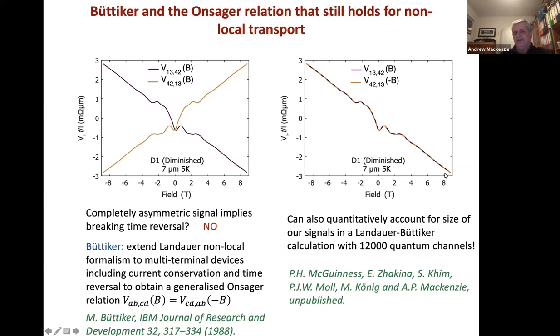And so what that's telling you is that, and Philippa has confirmed this with a very elegant Landauer-Büttiker symmetry analysis based on the symmetries of our situation. It tells you that you're not breaking any fundamental symmetries there in what you're seeing, but that things can be remarkably strange when you're looking in low symmetry situations in fields in the ballistic regime. So all of that's in our thesis.